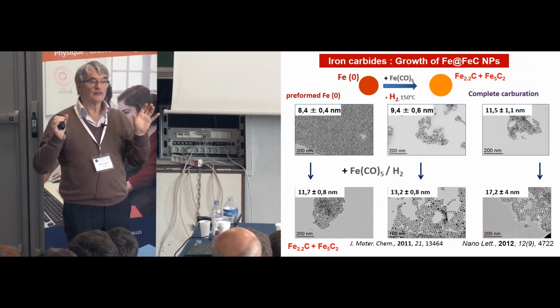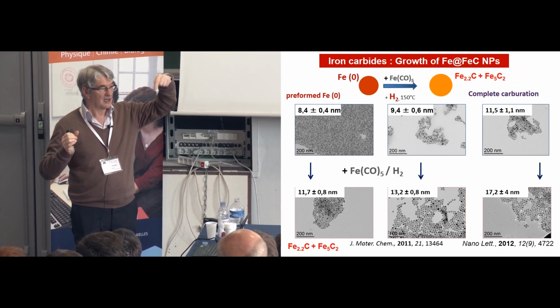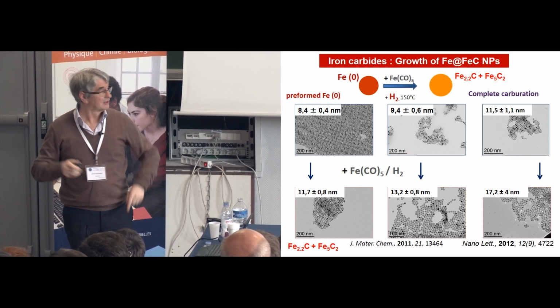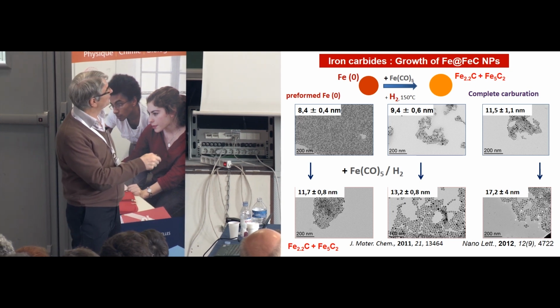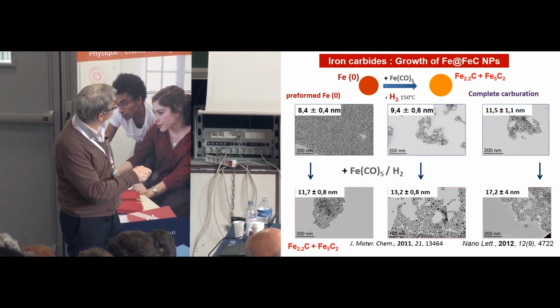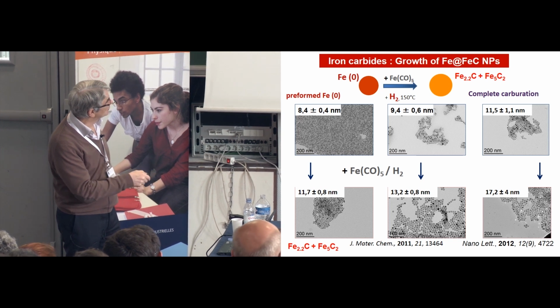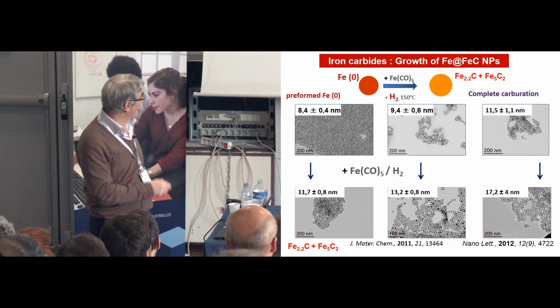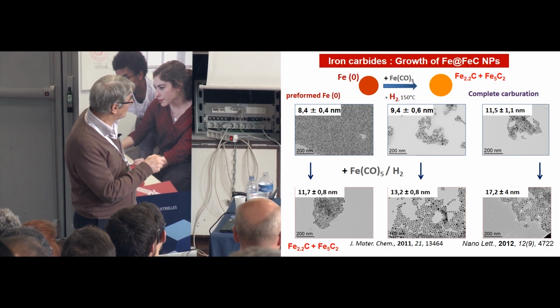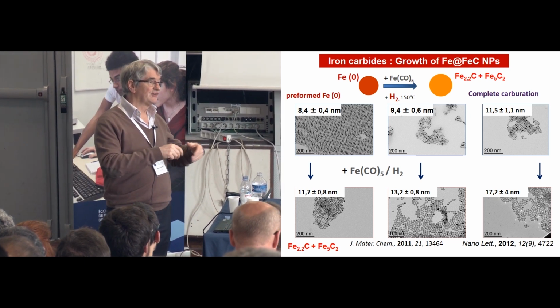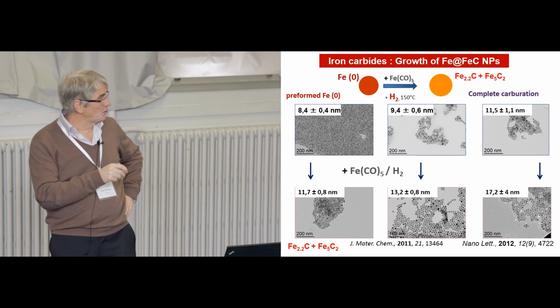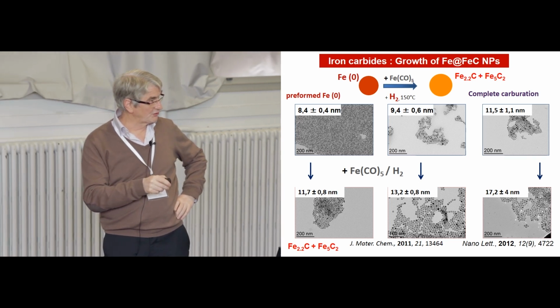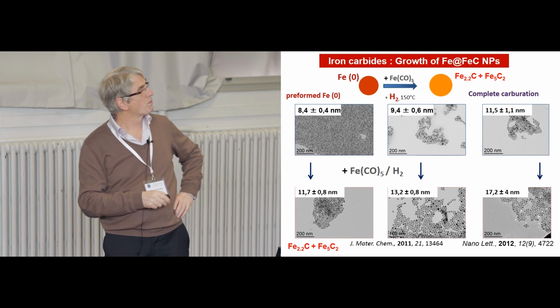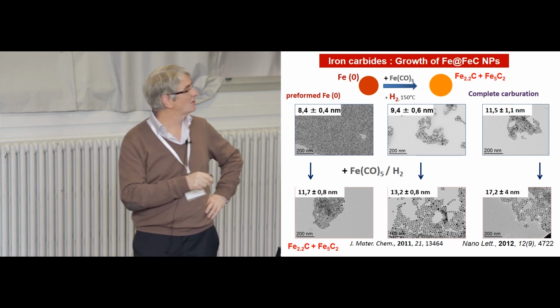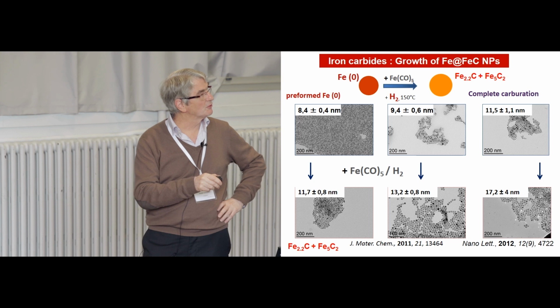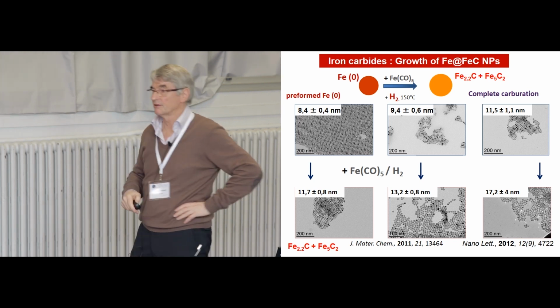And when you do the Fischer-Tropsch process, carbon gets inside the iron. So we did that, little homemade Fischer-Tropsch, and we grew the particle, and we got monodispersed iron carbide particles. If we don't use hydrogen, we can reduce CO by itself, and we put carbon, but it's less efficient, so we make core shell nanoparticles.